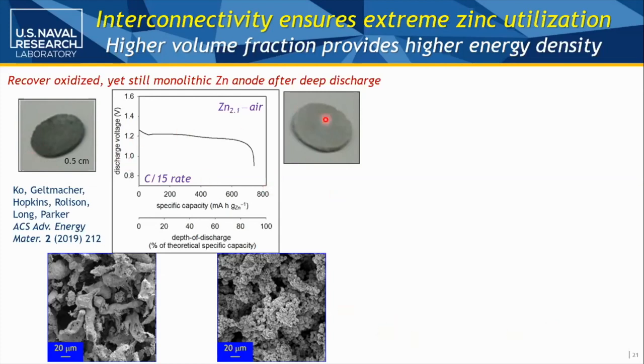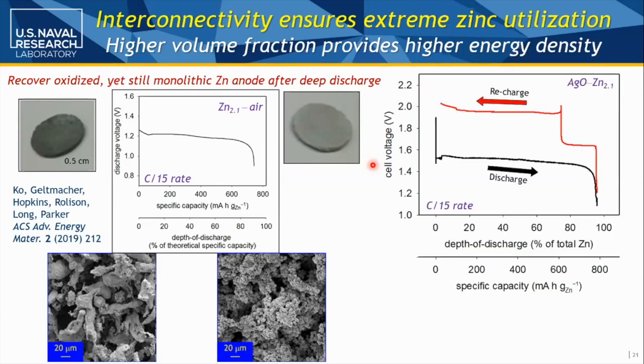Sponge goes in, sponge comes out, and now it's of course grayer because it's got zinc oxide. And now we're putting it versus a really homemade silver oxide, because the military loves silver zinc. Silver zinc kept the Apollo 13 astronauts alive. There's some uses for it, although it's not going to go in a car because people would be stealing batteries. So the same thing, you do a deep discharge, a deep recharge, you can see just how much you're working with.